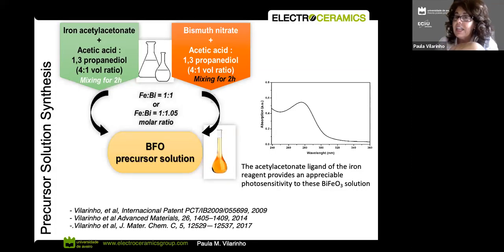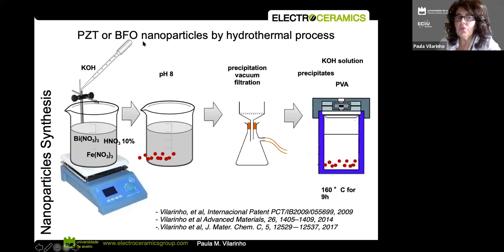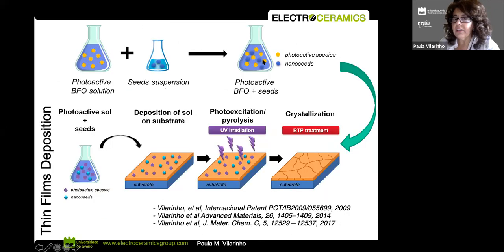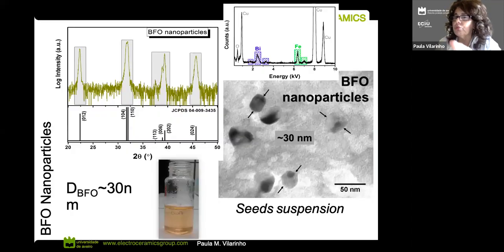So we develop a technology in which we somehow are able to decrease considerably the temperature of crystallization of these materials. And the technology is we use some nanoparticles that are produced by hydrothermal method, and then using these nanoparticles inside of our chemical solutions and using UV radiation and then rapid thermal annealing, we are really able to crystallize our films on the top of flexible substrates at very low temperatures. And that's what is represented here.